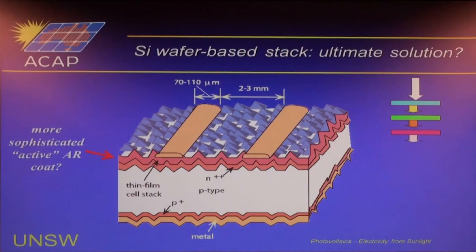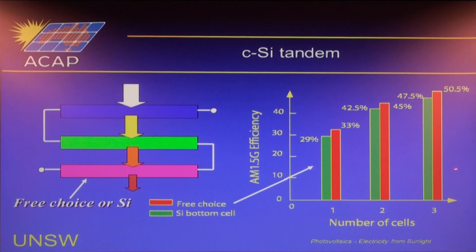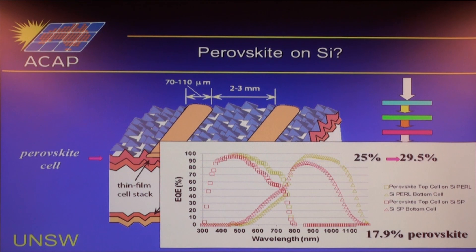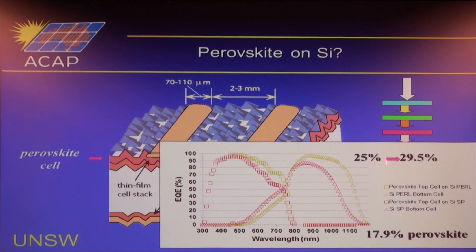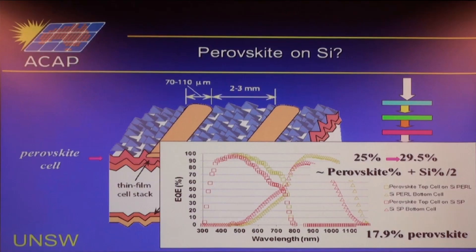We're very interested in applying perovskites to silicon tandem cells. By stacking perovskite cells on top of silicon, you go from a ~30% efficiency limit up to closer to 50% with two perovskite cells on silicon — potentially a practical cell of ~40% efficiency. Ibrahim's modelling suggests combining our best silicon cell with the best independently measured perovskite cell would already yield close to 30% efficiency at the present state of development, with reasonable efficiency possible even using lower-quality silicon cells.